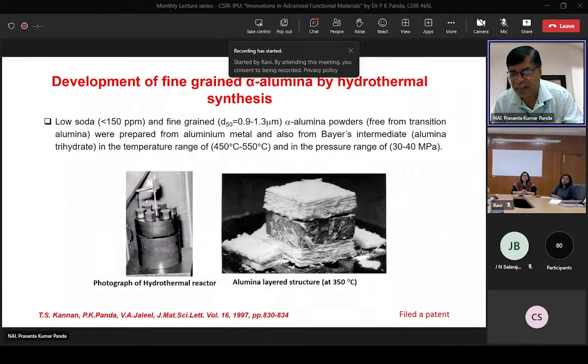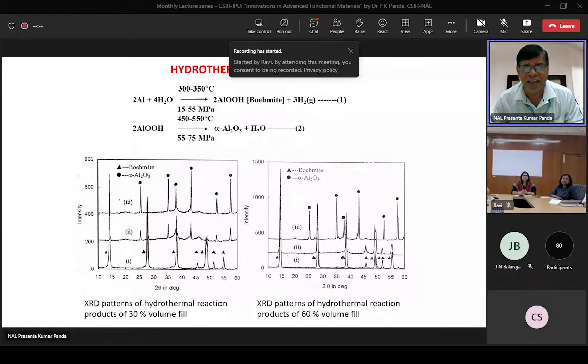Therefore, it was very interesting to generate, and we filed some 2-3 patents in this area, and this was also communicated. What is interesting here from the reaction is that initially it reacts with a metal and forms boehmite, and that boehmite has water molecules, which it releases straightforwardly without going into transition alumina, and it forms alpha alumina. Later on, this was changed actually.